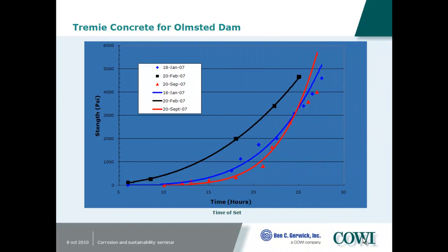So here was the strength gain with time. We had it heavily retarded here with a lot of admixtures, so it took a while for it to reach set. And then you can see within a few hours afterwards that we were exceeding our design strength, because you have to put an extra amount of cementitious material into the Tremie concrete to get the workability. So the strength is almost a byproduct. Reaching the design strength, as you see, was achieved within 1 day.